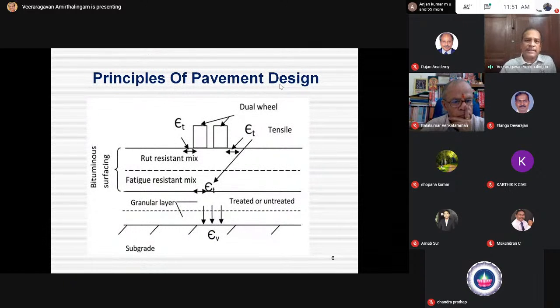So in a conventional pavement design, we consider the radial tensile strain at the bottom of the bituminous layer as a criteria relating to the fatigue crack. At the end of the design life, I told about the design life in the beginning, of 15 years or 20 years, the crack may initiate at the 10th year, 11th year, 12th year. But it takes time for it to propagate. At the end of the 15th year, this will have alligator fatigue crack. That means design life has reached: 20% cracking of the paved area will be cracks. Then the pavement life has reached.